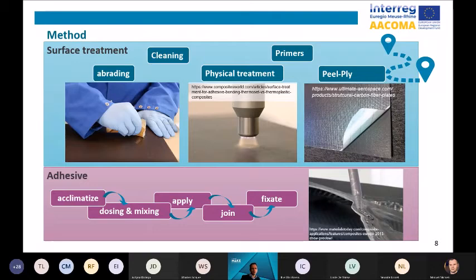For your treatment of the substrates, a proper treatment of the substrate is often underestimated. I dare to state that in more than 80% of the bonding failures, a wrong surface treatment is the root cause. In many cases, the finger is pointed to the adhesive supplier, but the quality of the adhesive itself is rarely the root cause.